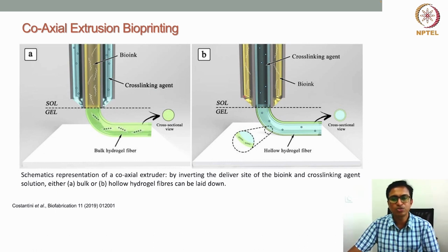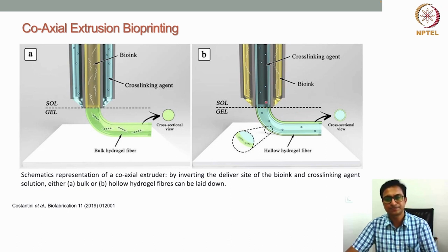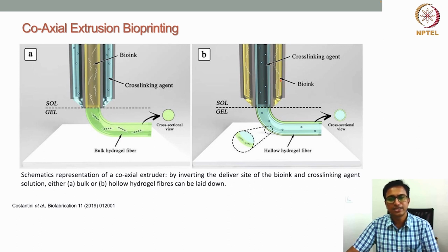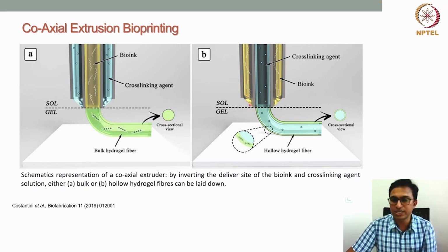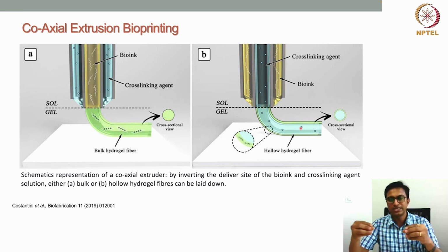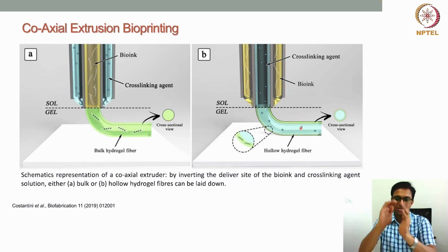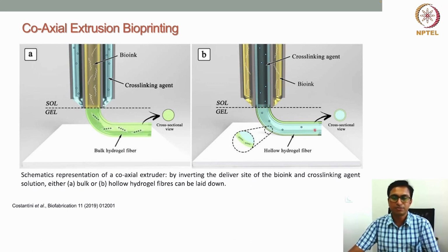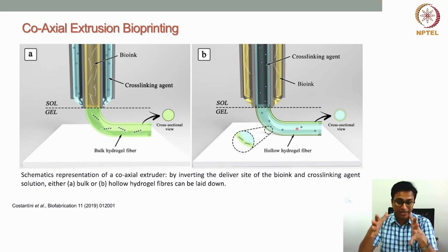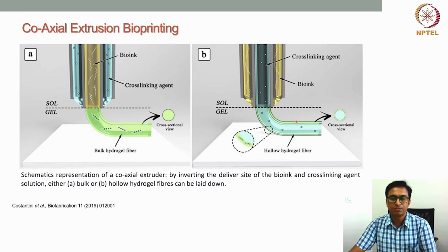Now in another case, we can put the cross-linking agent in the inner core compartment, and the hydrogel material can come out through the outer compartment. In this case, as they extrude together, the hydrogel will cross-link from the inner core, from the inner part of the hydrogel. So while the earlier case gave a bulk hydrogel fiber, in this case we get a hollow hydrogel fiber, because the cross-linking agent present in the core of the hydrogel strand prevents the material from coming together, preventing the bulk of the hydrogel and creating hollowness inside. So we can create a hollow hydrogel fiber.